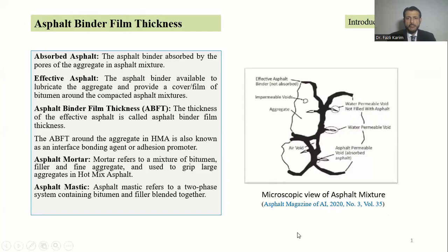So, asphalt binder film thickness. As you know, sir, asphalt is basically a mixture of coarse aggregate, fine aggregate, filler, and bitumen, and usually mixed in the asphalt plant at a particular temperature based on viscosity of the binder. And after mixing, the materials are usually transported to the site, placed, and thoroughly compacted to the desired density. So, in a hot mix asphalt, some of the bitumen is usually absorbed by the pores of the aggregate, which is called absorbed asphalt, and some of the bitumen is used to produce a coat of bitumen on the aggregate surface, thereby lubricating the grains in the asphalt mixture. And this binder content is called effective asphalt, and the thickness of the effective asphalt is called asphalt binder film thickness. So the current research is totally linked to the asphalt binder film thickness in asphalt mixture.